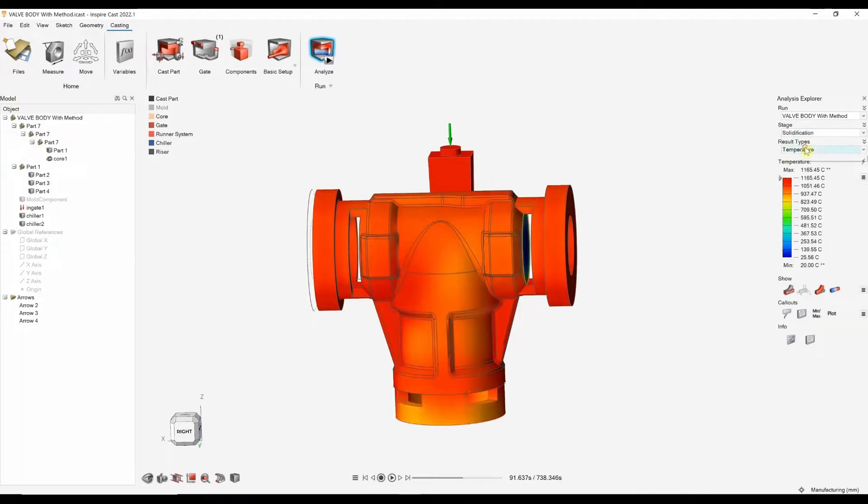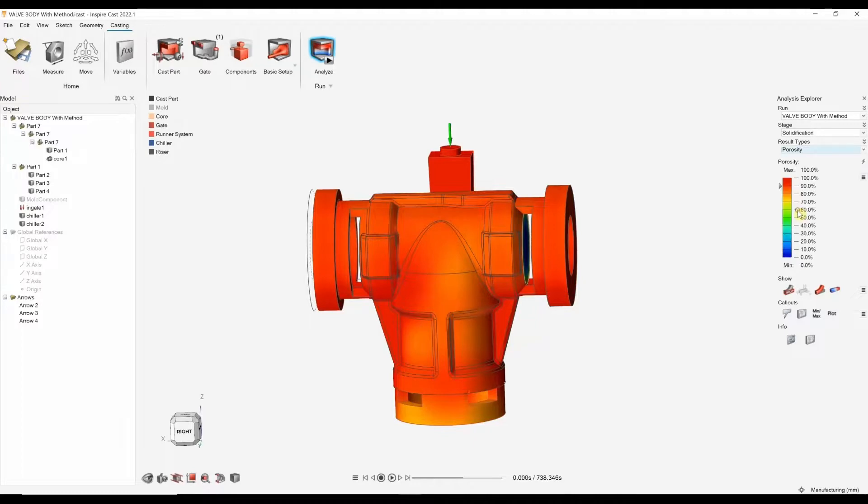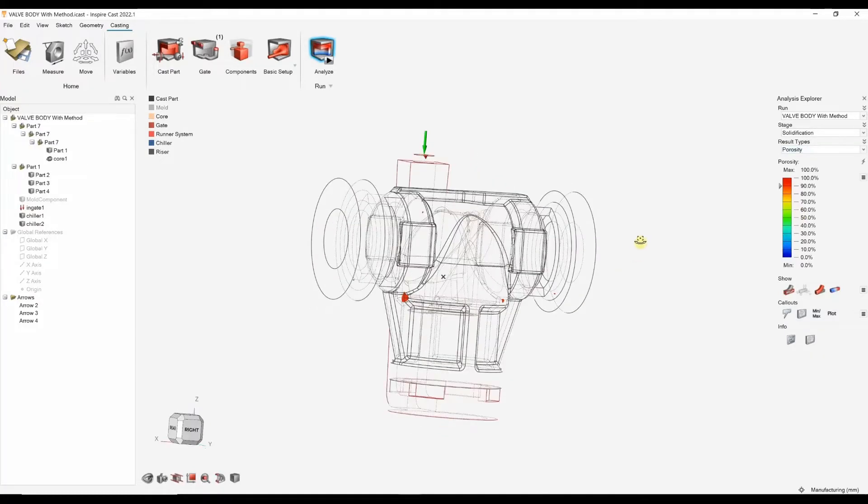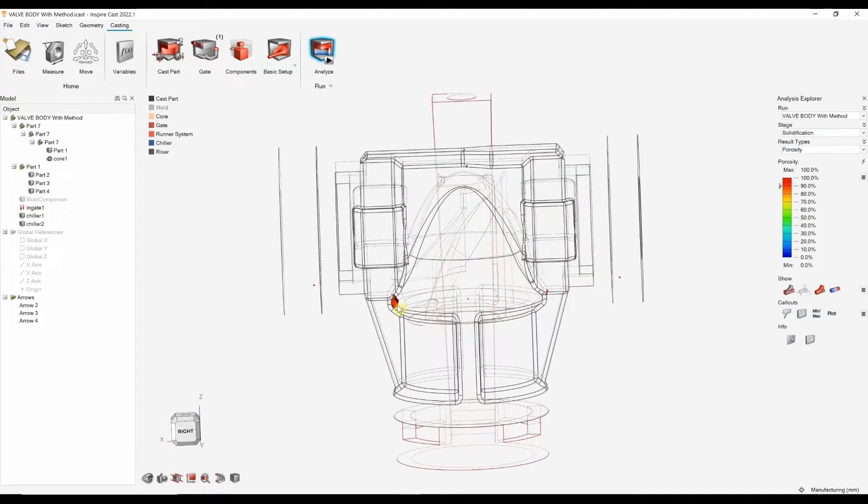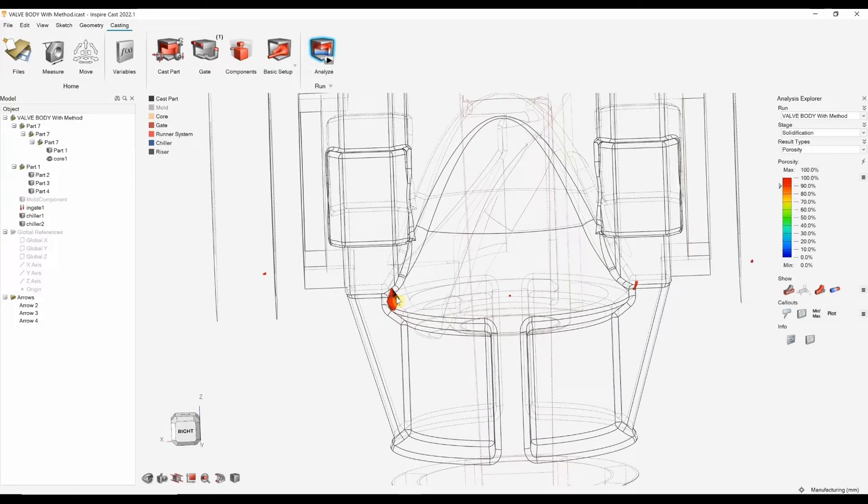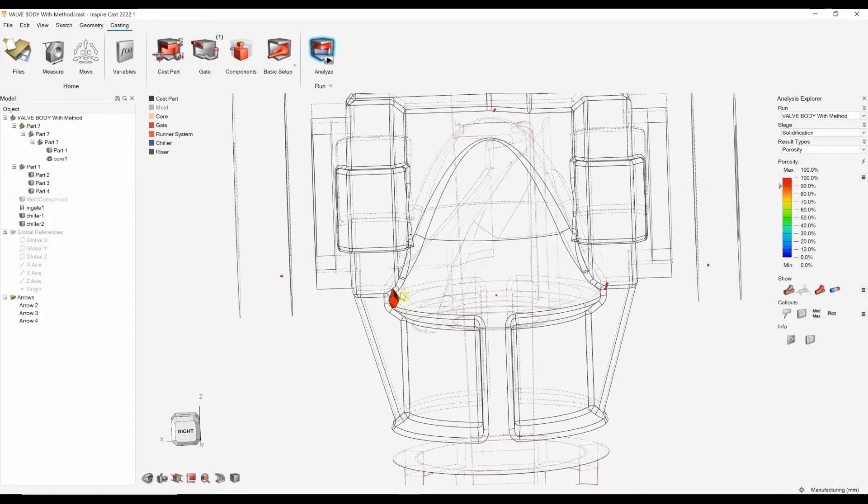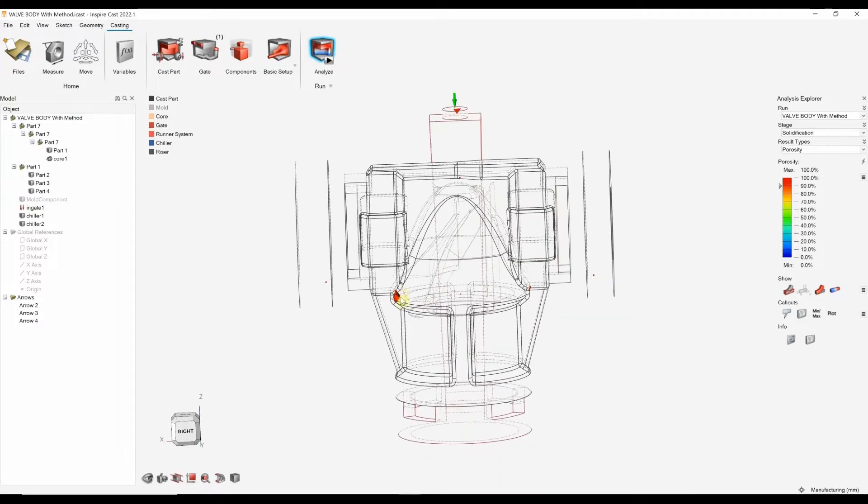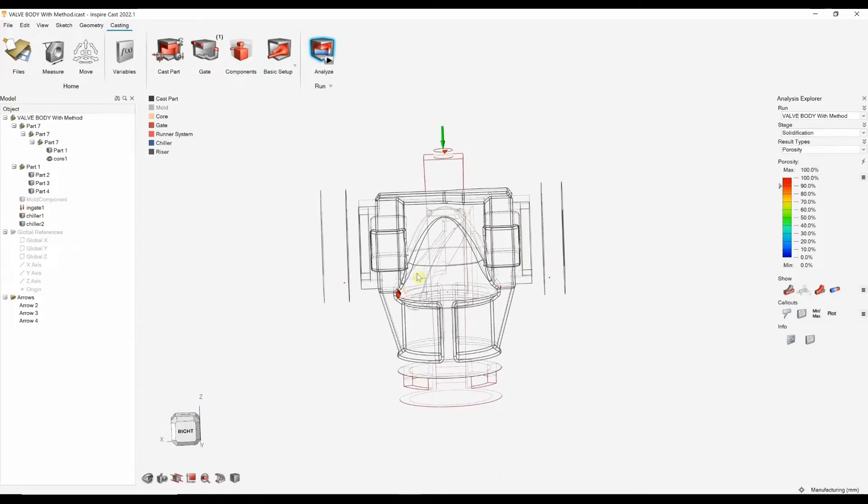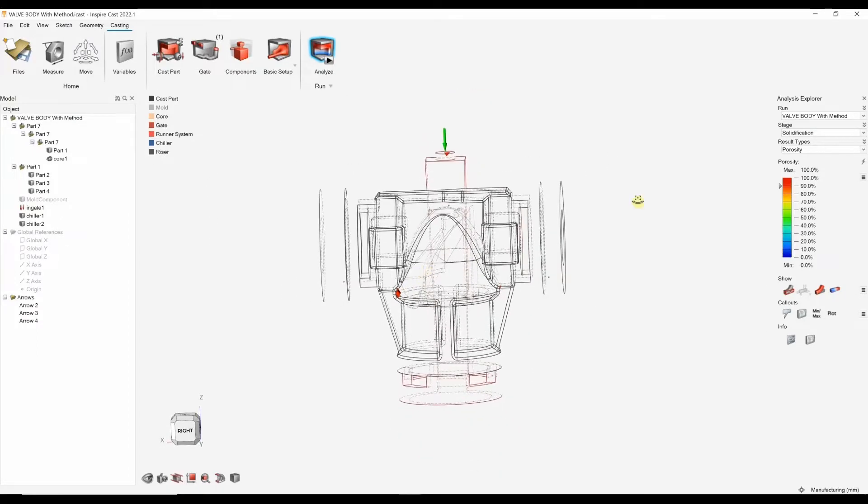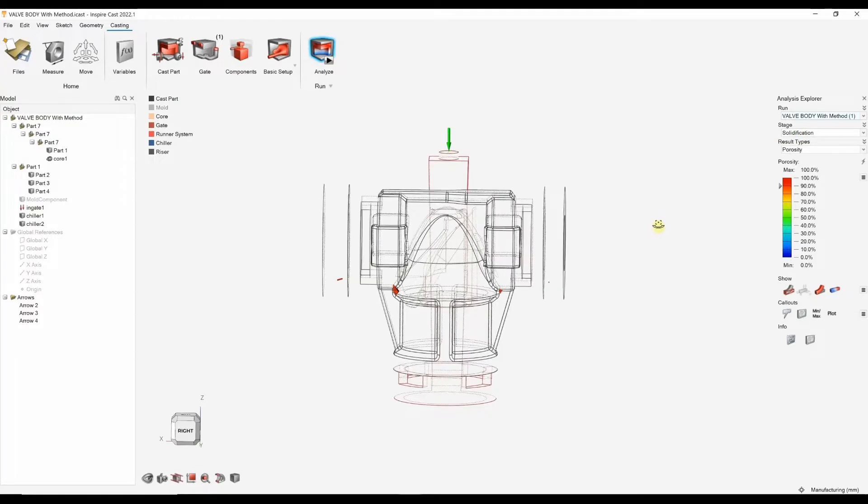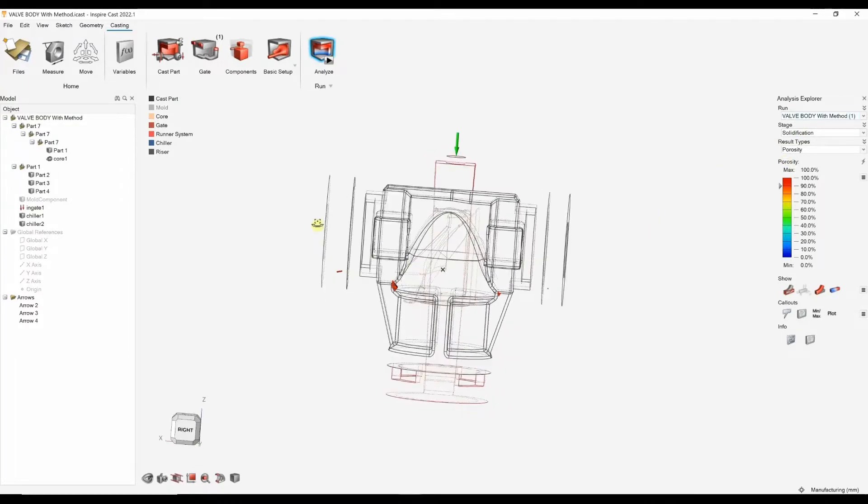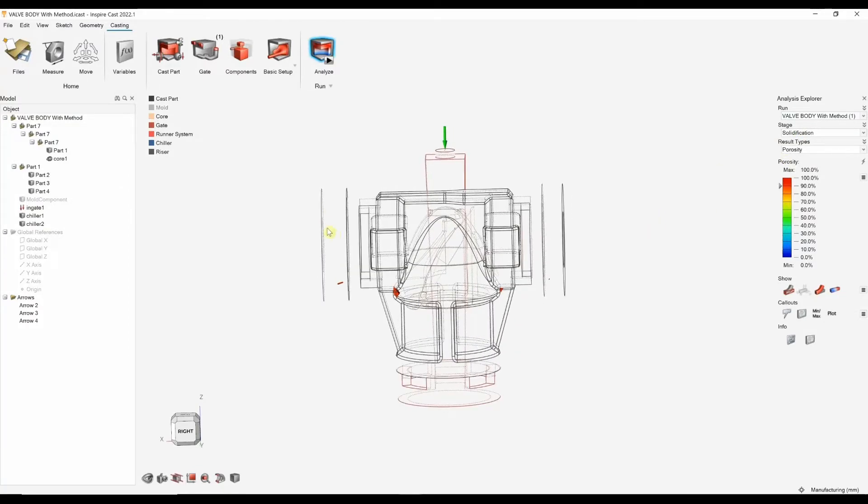We're looking to try and reduce, hopefully this porosity is reduced. You can see here that's definitely reduced. But we are still seeing some porosity in this location. So, obviously, this location is thicker. One of the methods we tried was just to increase the size of this left riser. If we snap to this second run, we increase the size of this left riser ever so slightly. Didn't really do much to draw out that porosity.